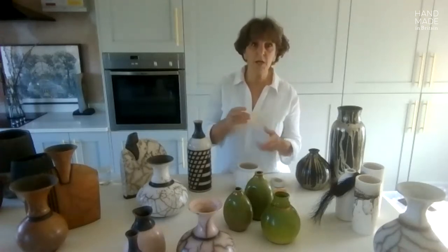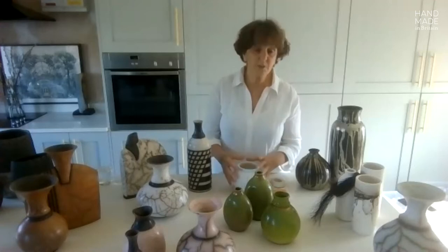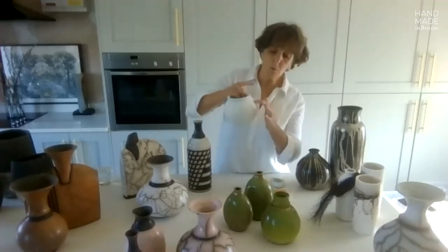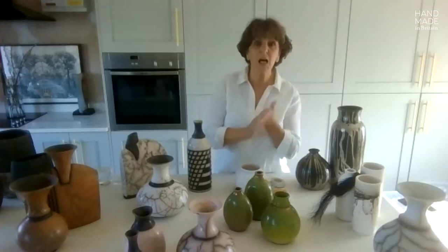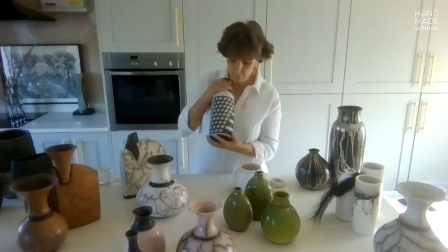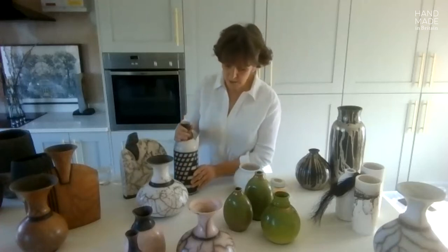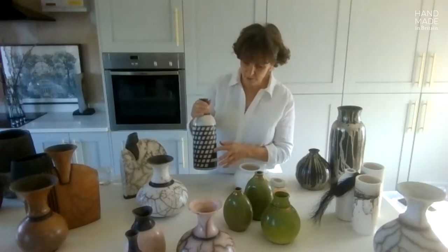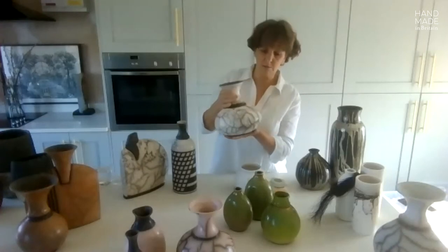There are other materials — I've tried damp paper and larger wood pieces. After 30–40 minutes it's removed from the sawdust pit and left to cool at ambient temperature. At that point all of this material shivers and falls away from the pot, and it's only at that point I know what I'm going to end up with — whether this is going to have worked. So it's quite a planned process, but the markings — other than where I've masked — all of these lightning markings are completely and utterly unique and random.